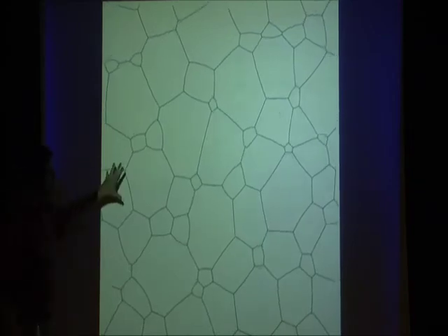Another is, if you look at this final image, it's about to get there, this structure looks completely different than the way it started. It actually started from a Voronoi tessellation using randomly distributed points in the plane. These are just distributed according to a Poisson distribution. It's a uniform distribution. The end result was completely different.